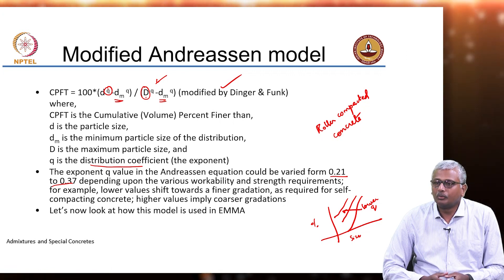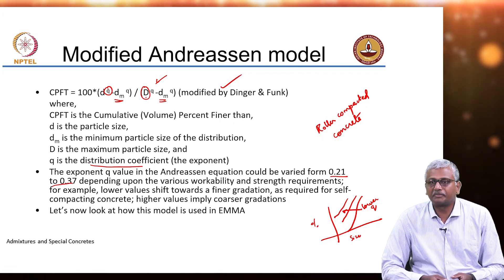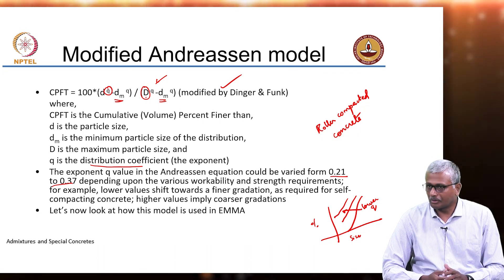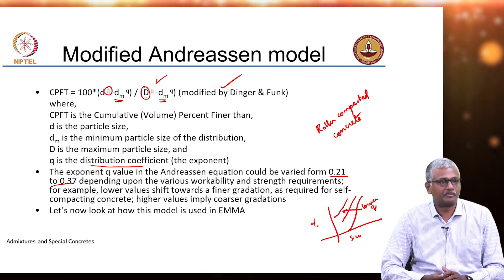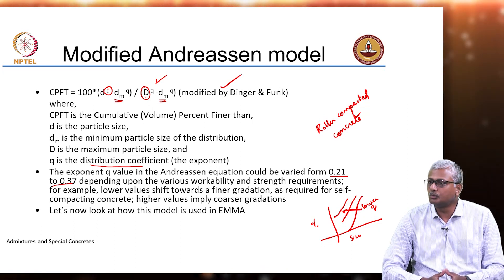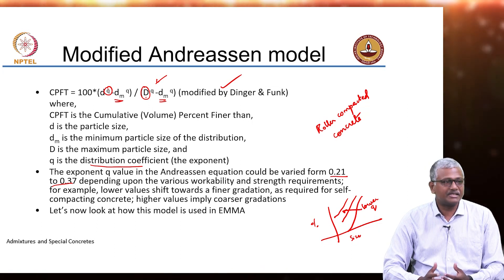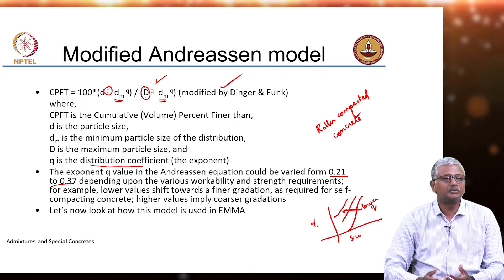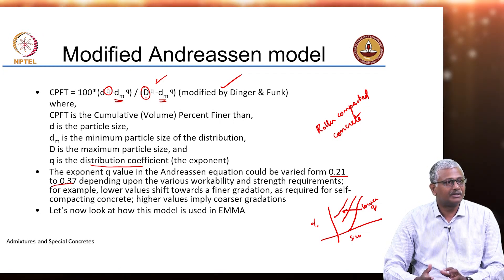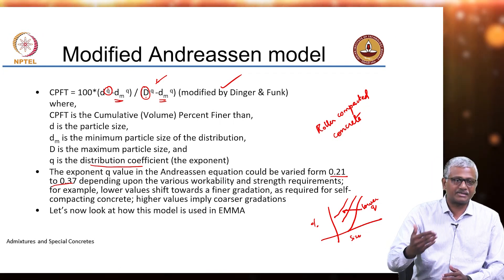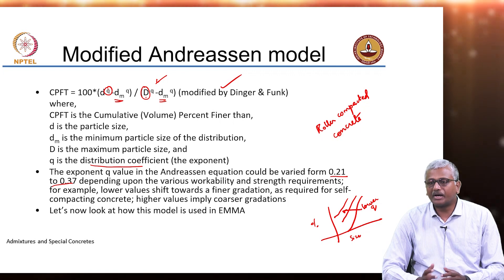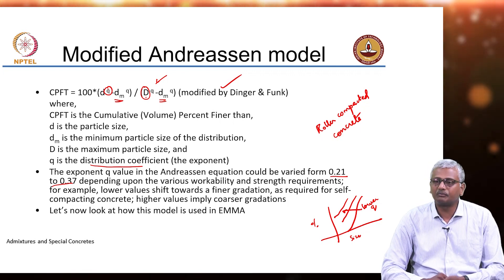Good morning. We were talking about how particle packing approaches, which are typically used to design compacted powder mixtures, could also be used to design concrete mixtures for high performance or high strength concrete. The idea is to design concrete mixtures with the view of providing a system that has the least voids, selecting particles of the right sizes that fit into the gaps offered by the next higher size, coming to a more compact system which requires less water to provide the given workability.